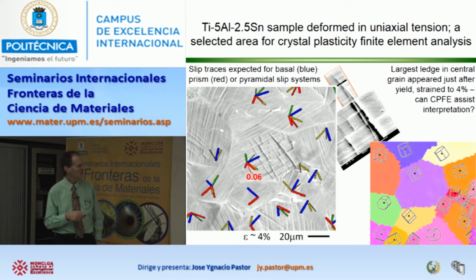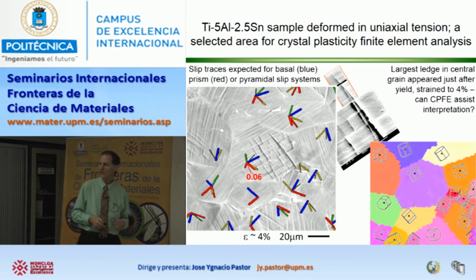But we also see these very strange features. These are like huge ledges that show up in the middle of a grain. And they show up in a few other grains too. They're not typical, but they're not uncommon either. Maybe 1 or 2% of the grains show this. So is this damage? Is this a crack? What is it? And we wanted to pursue that.